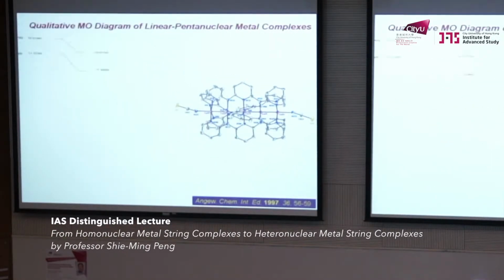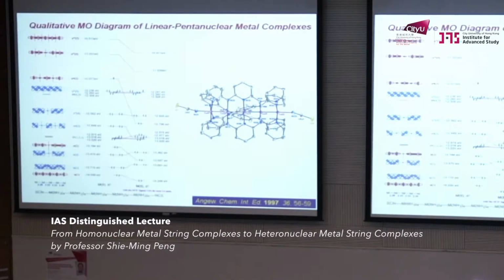So the extended Hückel calculation shows the sigma bond, non-bonding, anti-bonding, and the rest all populate. So 35 electrons will populate up to the sigma non-bonding. So the whole complex only has 1 unpaired electron, magnetic moment of 1.9, and the 2 anti-bonding orbitals are empty. That means we have a bond order of 2 among this pentacobalt moiety. So each cobalt has a bond order of a half with sigma character.